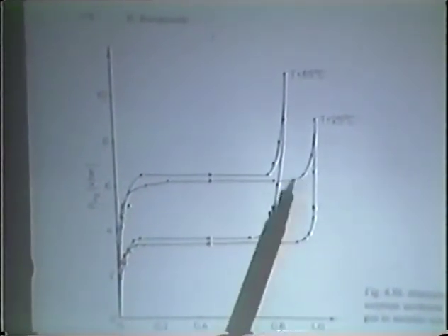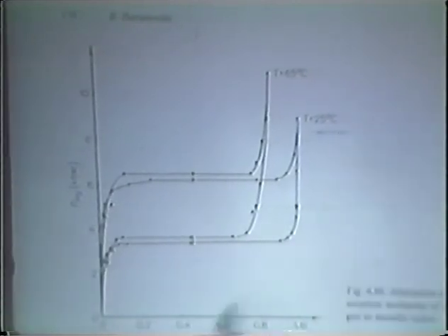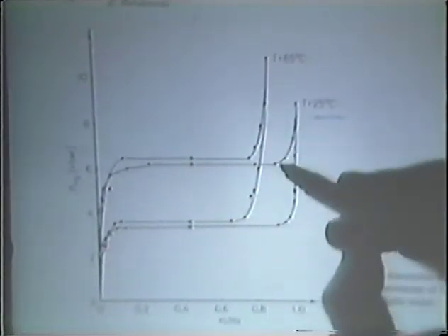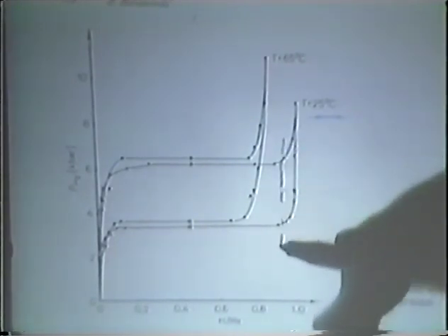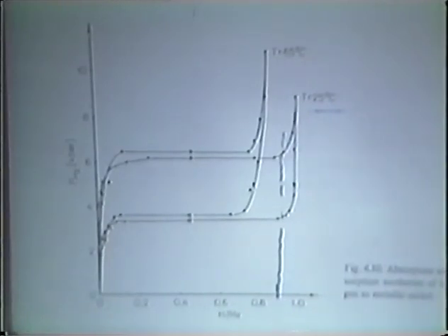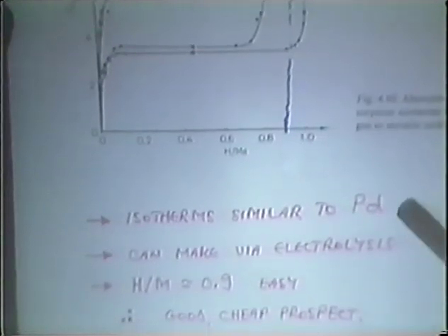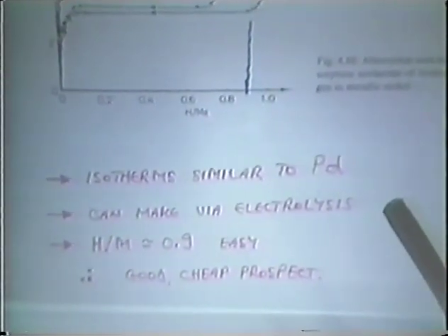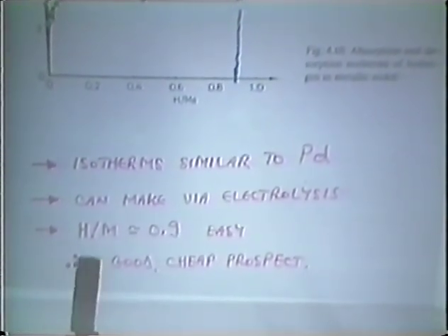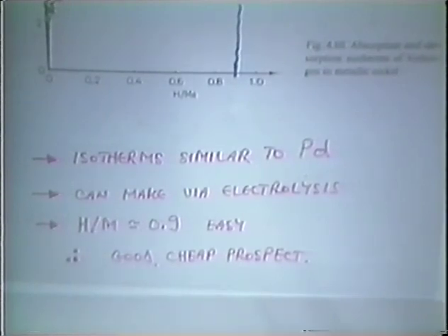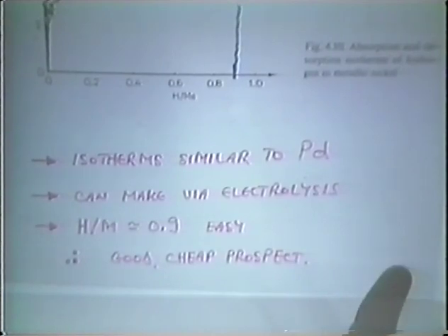Now, some of you are aware that the phase diagram for hydrogen and nickel is very similar to the phase diagram for hydrogen in palladium, except for the fact that you have to raise the pressure to 6 kilobars, gas pressure, before hydrogen flows in and you convert from the alpha phase to the beta phase. But at 25°C, as you can see, you can convert at 6 kilobars, you can drive in hydrogen, and before you have to push harder, you can achieve a hydrogen to metal atom ratio of 0.9. So the isotherms are similar to the isotherms of palladium except for the pressure differences. You can produce the nickel hydride by electrolysis. You can achieve a higher hydrogen to metal atom ratio, and therefore this would look like a prospect for trying to observe cold fusion experiments.